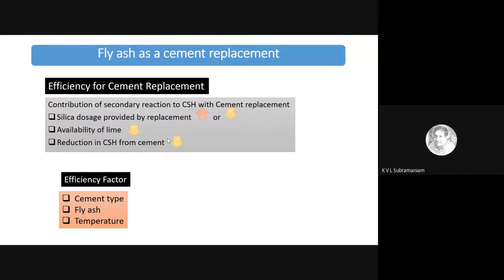So basically, when I add fly ash into cement, or when I'm replacing cement with fly ash, I may gain some silica into the system because fly ash is bringing in silica, but of course I lose the calcium component, because as I remove cement, cement is primarily calcium silicates or calcium aluminate. The calcium that is coming from fly ash is very small, so the calcium content decreases. And I lose out on the calcium silicate hydrate that the cement I'm replacing would produce.